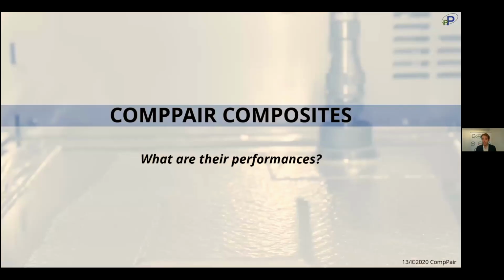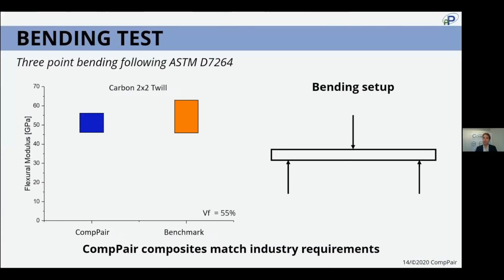So you have seen how we can heal most efficiently those composites, and most importantly extremely fast. But something that can be really important for you is also to see what are the performances of those composites in typical mechanical properties. So what we have done is to assess the mechanical properties of CompPair composites into tensile, into bending properties, but also compression after impact or even fatigue, to see how they perform. And so what we have done is to run those tests, and we just want to present you a few of them in here.